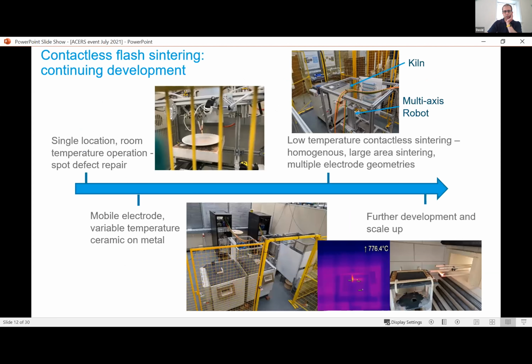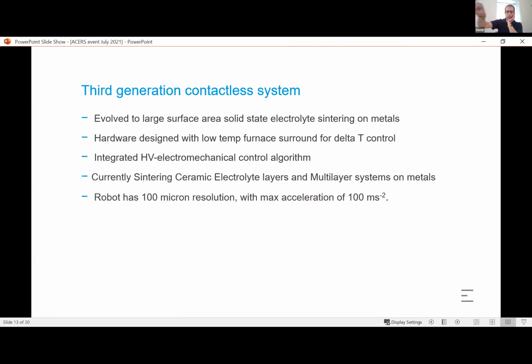What we've done though, I'll skip through, is we've actually now gone from looking at repairing these glazes to actually sintering solid state electrolytes on metal and on various substrates. So we've got a robotic arm that's synchronized with the nonlinear controller, whereby we insert an electrode into a low temperature furnace, and we can control that really quite accurately.